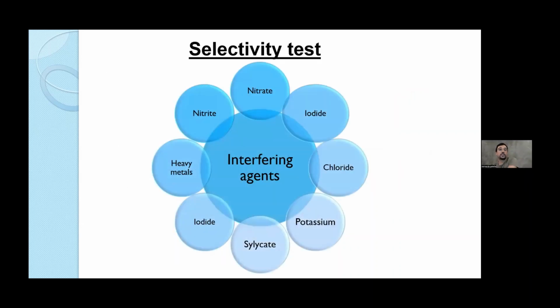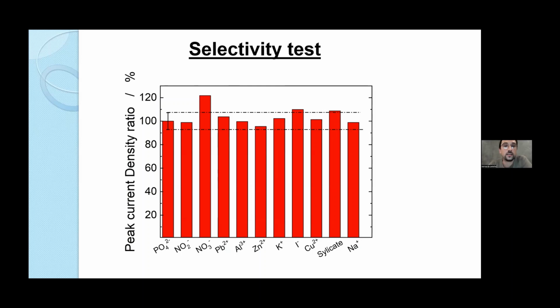So then we have carried out selectivity tests simply by adding to the solution different chemicals such as nitrates, iodide, chloride, potassium silicate, heavy metals, and nitrite. And as it's possible to see from this image, the peak current density ratio is still fluctuating within the 7.2% error that I discussed before, except for nitrate ions. So we have a kind of effect of these ions on the detection of phosphate ions, but we are still trying to understand why there is this interference.